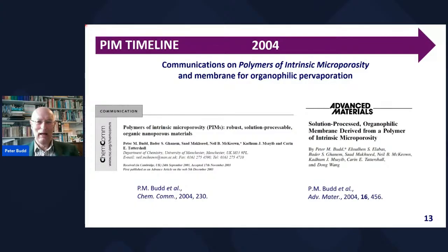And also the first membrane application. Because I'd been looking at zeolite membranes for hydrophilic pervaporation, the obvious thing for us to look at quickly was membranes, but in this case, we have a polymer which is hydrophobic, and we were looking at organophilic pervaporation. In fact, we were looking at removing phenol from aqueous media. So 2004 were the first communications on solution processable polymers of intrinsic microporosity that could be readily processed from solution into membranes of one form or another.